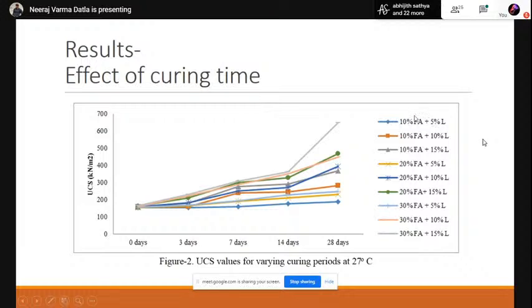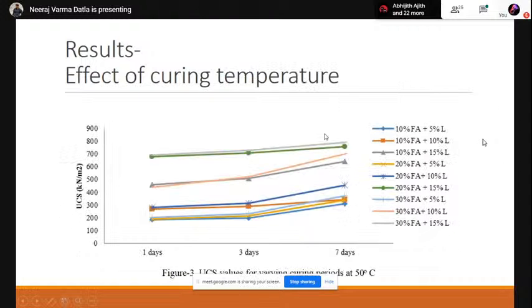However, with increase in the fly ash content also, more silica and alumina is available, so that we are able to get a higher strength at higher contents of fly ash and liquid activator content. And with respect to the temperature, with increase in the temperature, the enhancement in the geopolymerization takes place, and finally the final strength is going to increase.